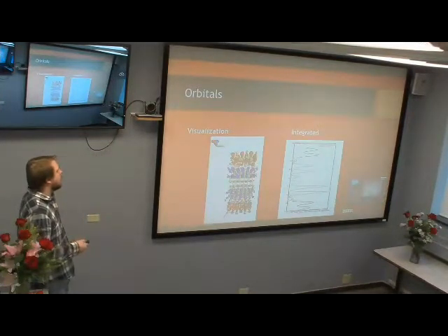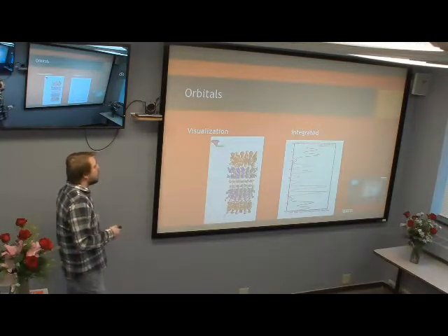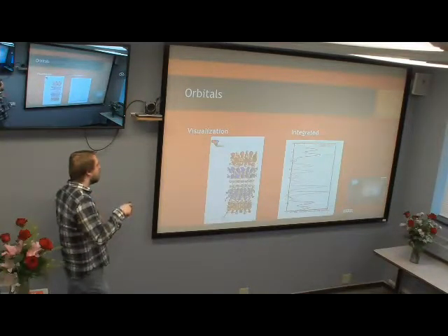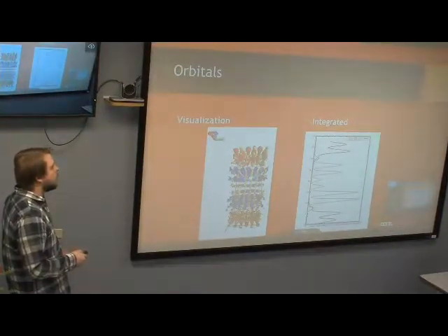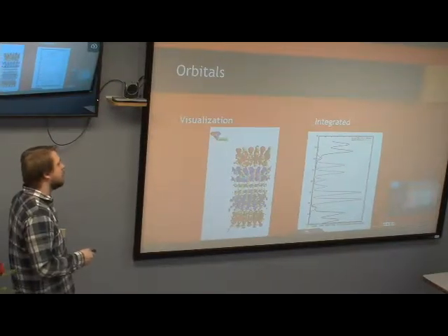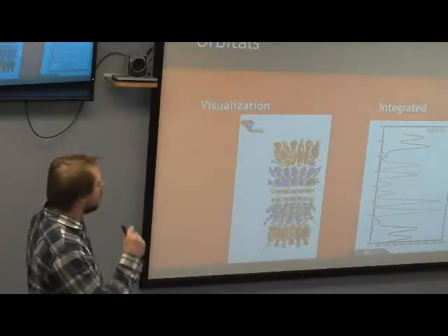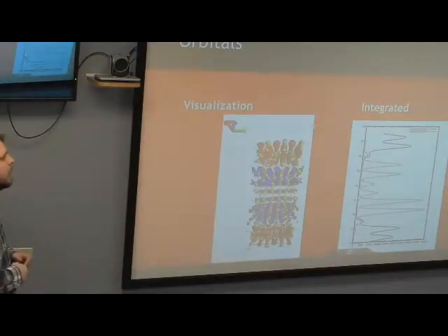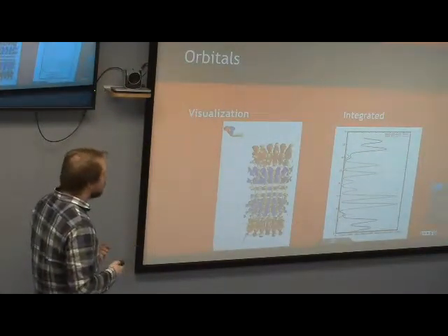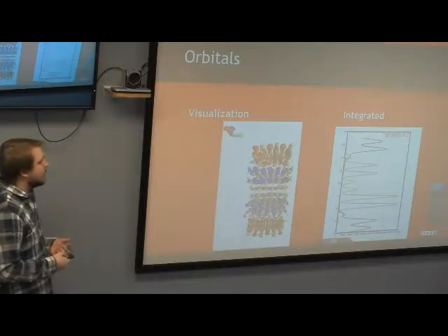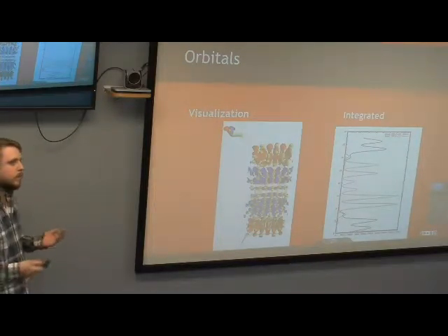At first, I was not entirely sure how to explain that, but what I tried doing, unfortunately, after I put the presentation together, was I looked at the LUMO+1 and the HOMO-1 and plotted those orbitals. And what you see is actually the reverse of this. The HOMO, like before, is localized around the p-dope, and the LUMO is localized around the n-dope. So it could just be that since the energies are pretty close to each other, when you heat it and run molecular dynamics, there's some kind of switching back and forth between the different energy levels. But between this and the fact that earlier there were empty valence band states kind of makes me want to study this further and verify any of this.